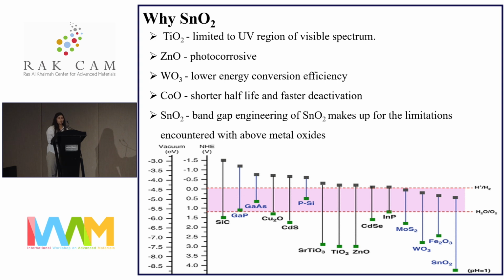Literature has reported a number of metal oxides to be used as photocatalysts for water splitting methods, out of which TiO2 is the most common metal oxide known in this context, but it has a limitation that it can only absorb in the UV range of the spectrum, which limits its quantum efficiency. Then ZnO is associated with photocorrosion, and WO3 has lower energy conversion efficiency due to the lower value of its conduction band. Then CoO exhibits shorter half-life and hence faster deactivation.